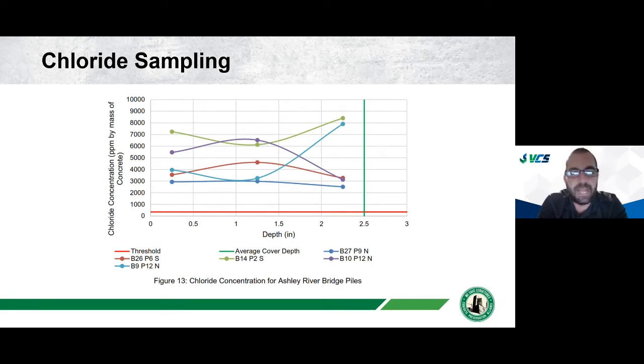When you see lines that are pretty flat like this, that tells me chloride penetration is very fast. And that's typically because there's cracking and damage. So as the concrete becomes cracked and damaged due to corrosion, it lets more and more water and salts into the structure, deeper into the structure. And so what you'll end up getting is a flatter chloride profile curve like this. And so, obviously that is a sign that the damage on the structure is quite advanced. And the risk for corrosion is widespread, obviously based on that corrosion potential survey that I showed.